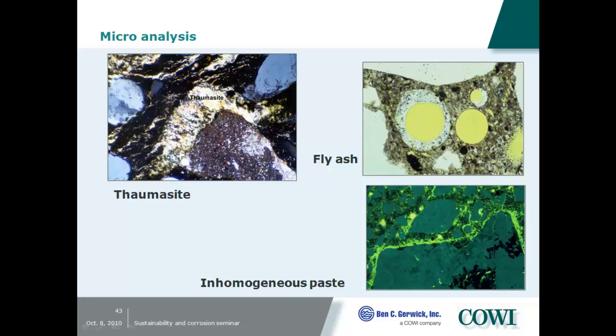When we talk about water cement ratio, you can measure an average when they add the water. But if they forgot to pre-wet your aggregate, they might have a porous zone around your aggregate like that. So in this one, the average water cement ratio might be very good, but you could have more or less motorways through your concrete, affecting also your durability.